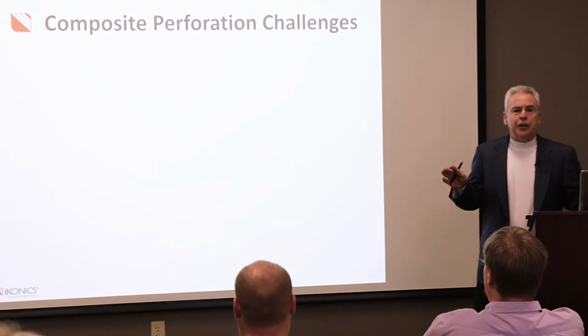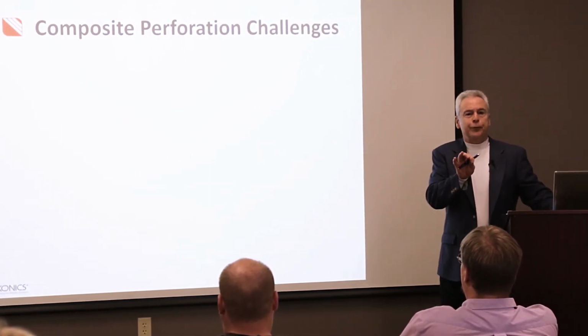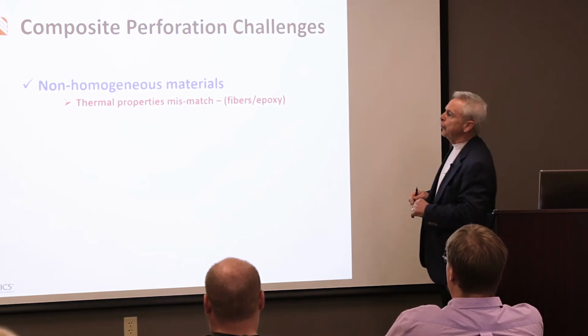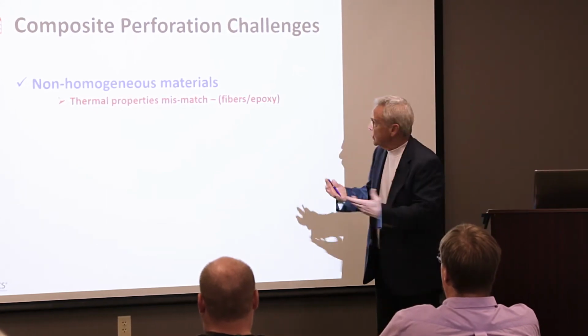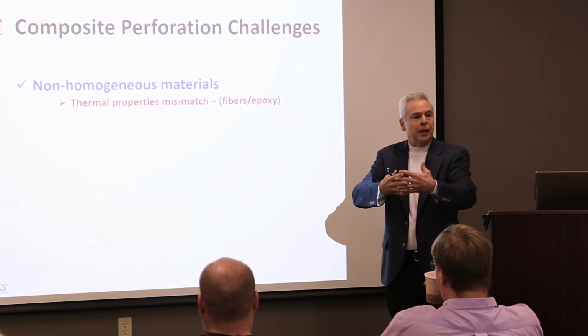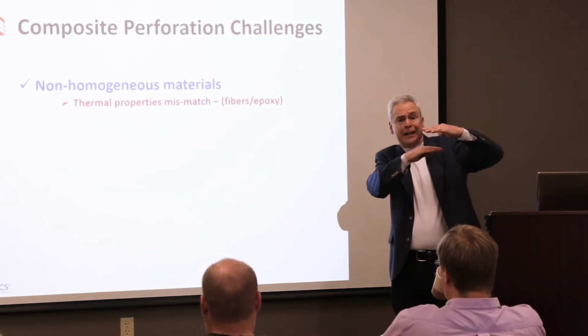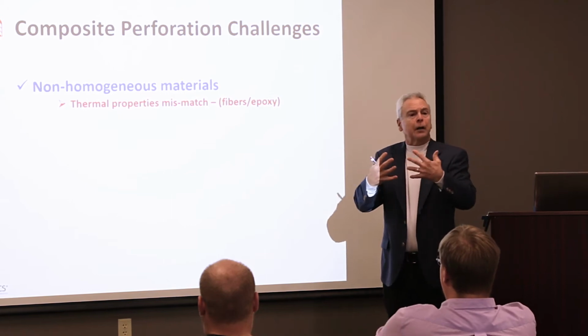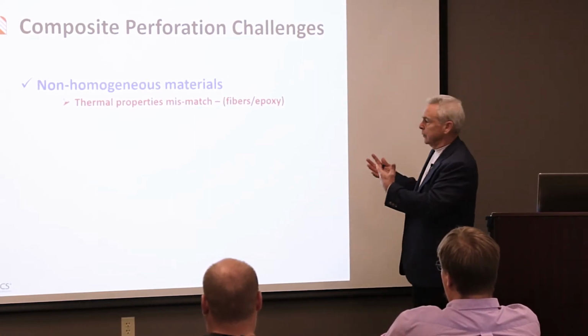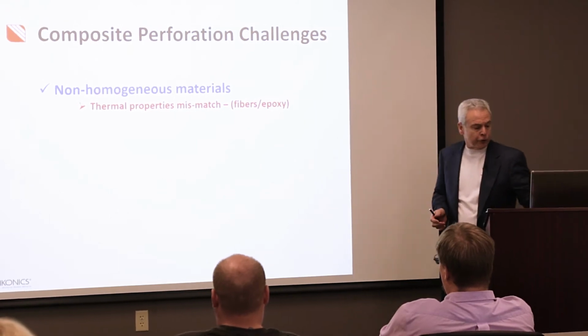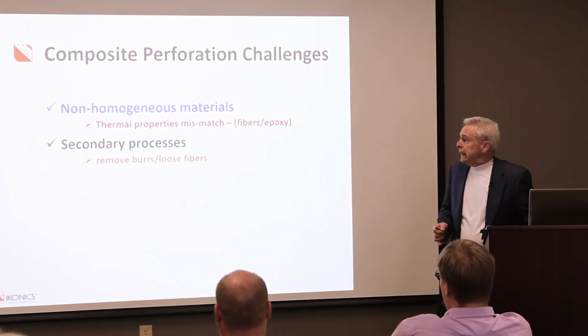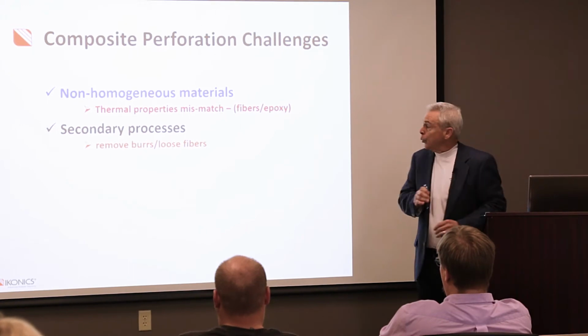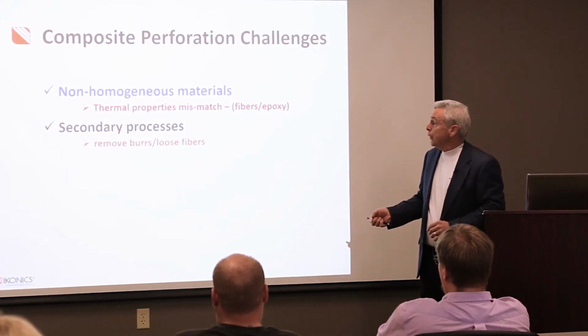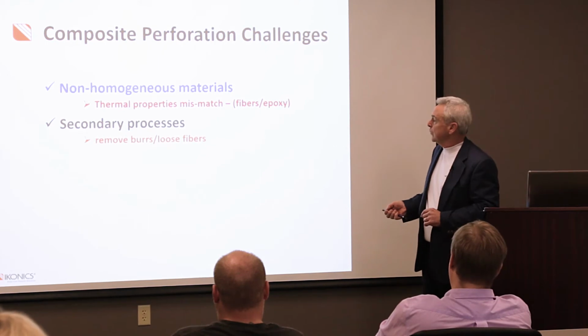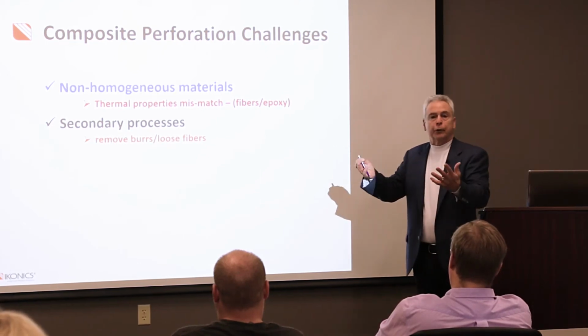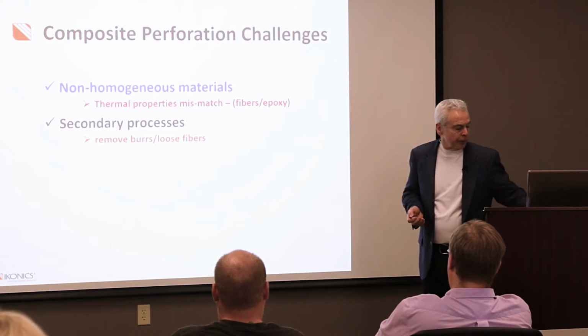Now, the challenges associated when you perforate composites are a lot different than with metals. For example, you're dealing with non-homogeneous materials. These materials are made up of fibers, epoxy materials, and they're also multi-layered. Different kinds of fibers, which create a lot of the thermal mismatch when you try to machine these materials. So that's certainly an issue that we have to be concerned about. They often require secondary processes. What I mean by that is you have to remove a lot of burrs that are generated when you machine composites and loose fibers, which you don't want floating around in your equipment once you've done the perforation.